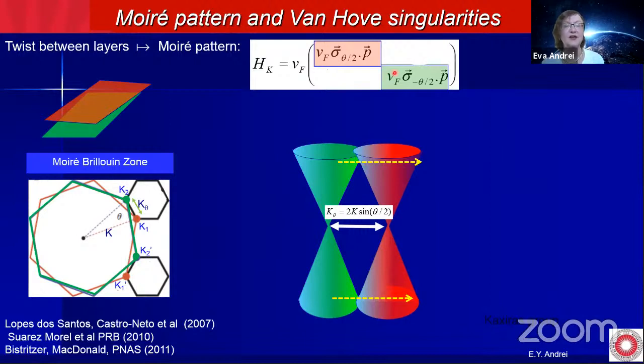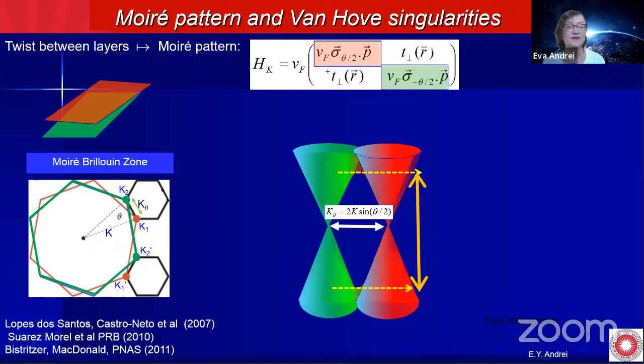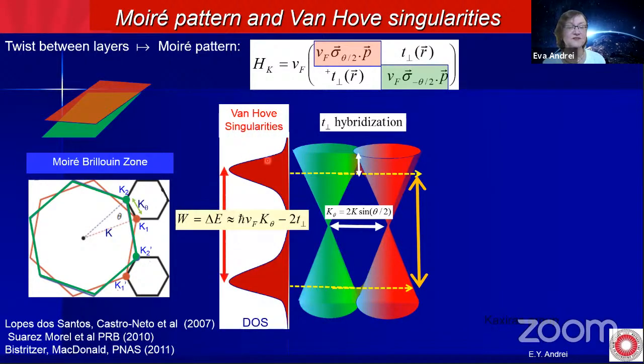If they don't interact, if they don't hybridize, they're completely independent of each other and they just go through each other. However, if we allow tunneling between the layers, which happens when they're very close, you get hybridization, and at the point of the intersection, you create a saddle point in the band structure, which gives rise to these Van Hove singularities, which we have seen in the experiment.